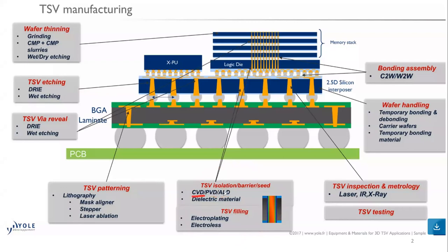You could do CVD, PVD, or ALD. CVD is the major one, and ALD is probably coming later. PVD I would not do, because it's not easy to form a uniform layer across the inside, unless the aspect ratio is not important.